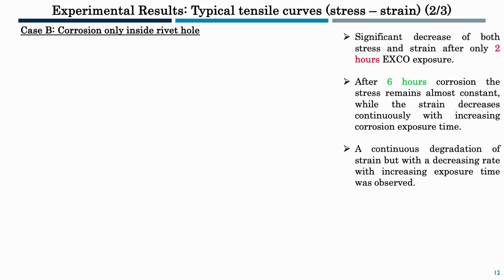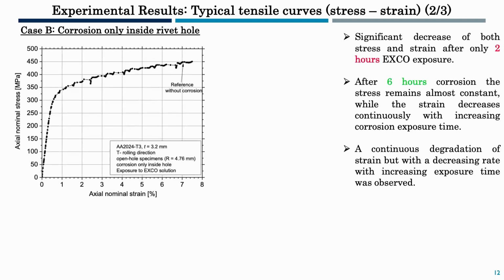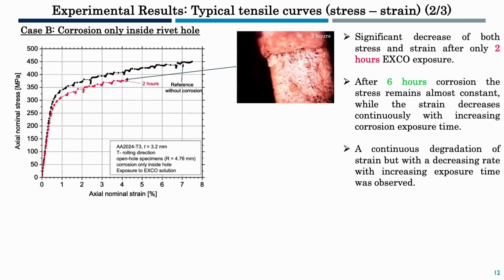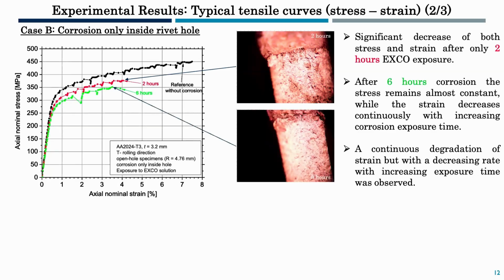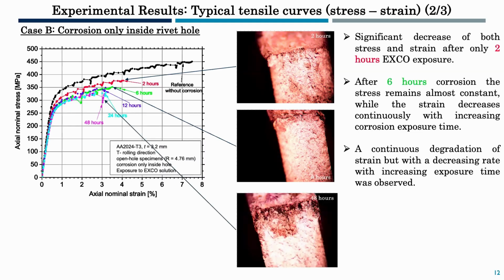Moving to the results for case B, corrosion only inside the rivet hole, again, a significant decrease of both stress and strain is noticed after 2 hours corrosion exposure. After 6 hours corrosion, the stress is not so significantly reduced, but the strain decreases continuously with increasing exposure time. But again, in the high exposure times, this difference is not so essential.